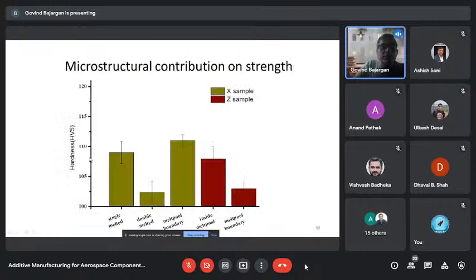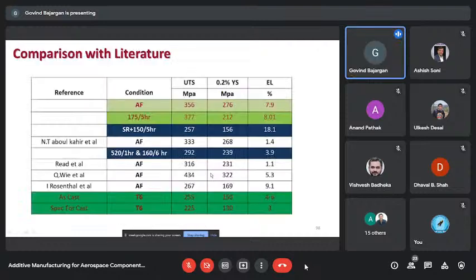It is well within ±5, which is very common in some materials. The very interesting thing is that the kind of properties we are getting is far better than what we can get with the conventional processes. I was a bit surprised because it was aluminum, and aluminum generally forms an oxide layer on the surface very fast. But in spite of that, what we found is that even the ductility is very good